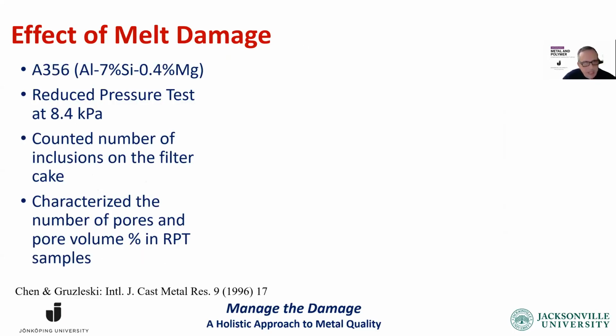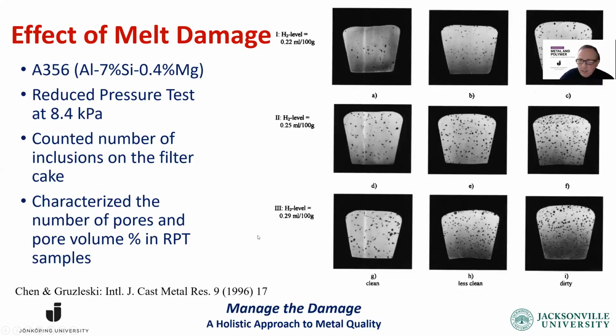So they had these reduced pressure tests, what they called clean, less clean, and dirty. I say moderately damaged, highly damaged, and extremely damaged. And different hydrogen levels. They are high hydrogen levels, but different hydrogen levels nonetheless. These are the RPT samples. We can see the difference, what the damage makes, and also what hydrogen makes. So the lower the hydrogen, the less the pores, but as we increase the damage, the pores increase.